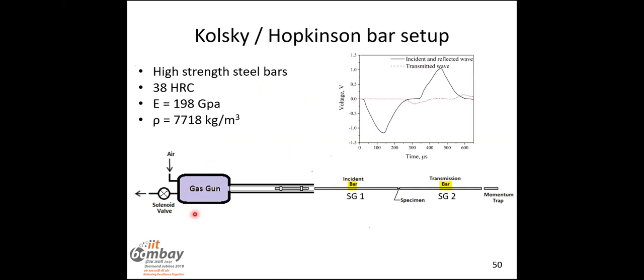So we use a gas gun. From the gas gun, we can have pressurized air. When the pressurized air is released, the striker bar will hit the incident bar. The moment it hits the incident bar, a stress wave will be generated. The stress wave will pass through the bar, and here we have the sample. Because of the impedance mismatch, some part of the stress wave will be transmitted through the sample, and some part will be reflected back. So here the main loading will happen.